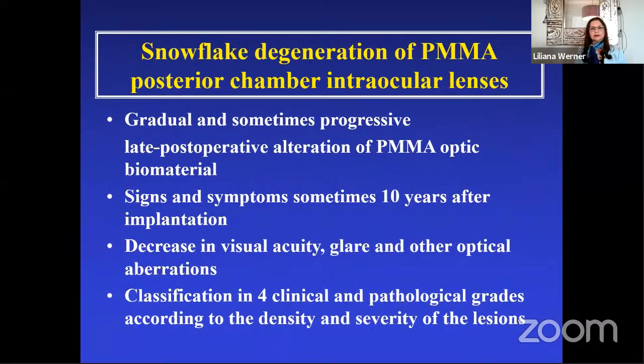This is generally a slowly progressive condition with signs and symptoms that sometimes take 10 years or more to be clinically significant. When the opacification of the lens is significant, the most common symptoms are decrease in the visual acuity and glare. This condition was classified in 4 clinical and pathological grades according to the density and severity of the lesions found within the IOL optic.